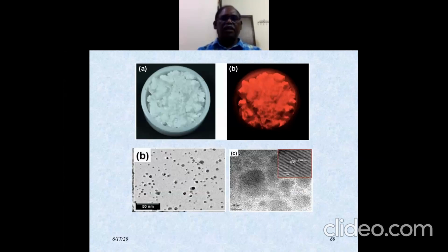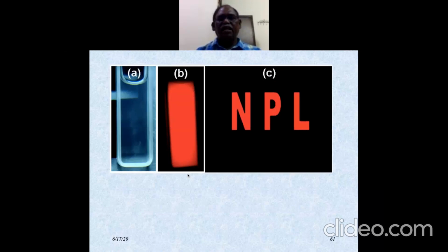So here you can see that in room light you don't see it, but under UV light you see a very intense color and very intense luminescence. And this slide again shows the nanoparticle size and all that, maybe around 10 nanometers or so they have mentioned. And here you can see that they have prepared the ink and then written this, which was done at NPL. So they wrote NPL. In room light you will not see this, but under UV you will see a very intense kind of color.